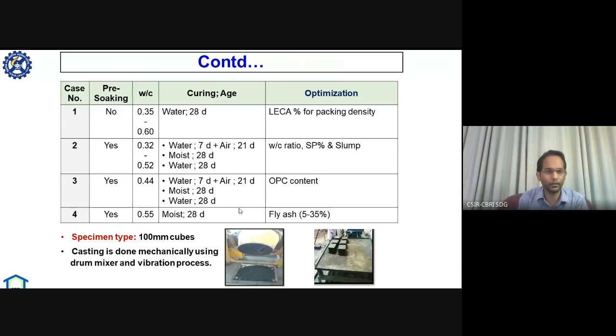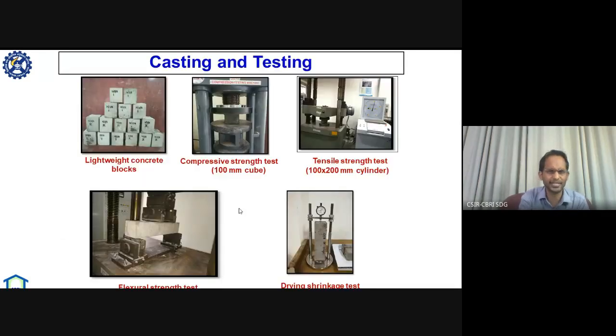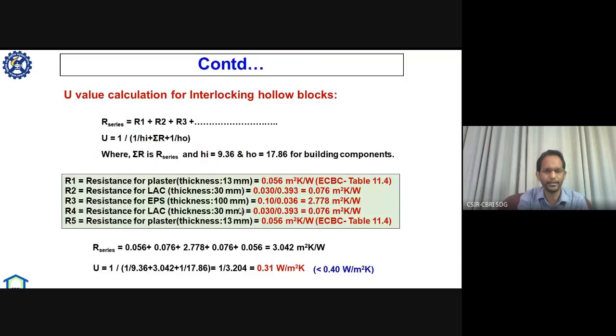To develop structural lightweight concrete, we have conducted several trials to optimize the percentage of LECA to be added, to increase the packing density, to decrease the void ratio, and to optimize the water cement ratio after adding the superplasticizer for a desirable slump value. So we have optimized for OPC. Our aim was also to reduce the OPC content by incorporating fly ash up to 5 to 35%. For that we have done casting and testing.